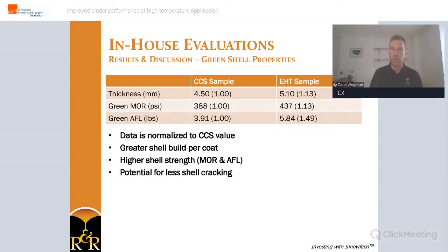So for example, the thickness of the CCS was 4.5 millimeters. That of the EHT is 5.1. So normalized, the CCS is 1 and the EHT is 1.13. And therefore, we can conclude that the EHT sample was 13% thicker. The EHT samples were significantly thicker while they were shelled with the same number of coats.